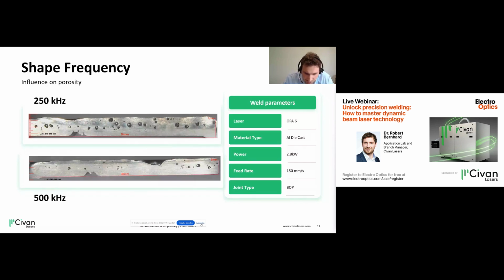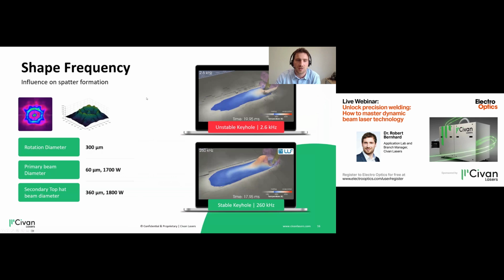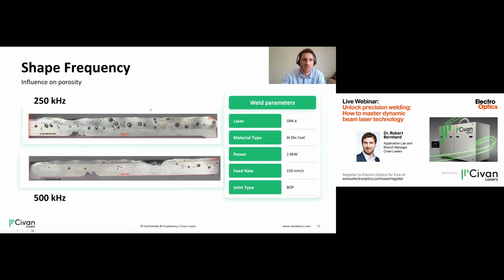Okay, so where were we? We were talking about shape frequency. And this shape frequency actually is not only on simulation, but also when doing aluminum welds. One personal favorite of mine is the welding of aluminum die cast. We're also going to talk about this more in detail, but to illustrate the influence on porosity, you can see that differences in the shape frequency, how the laser shape is generated, actually results in less or more porosity.